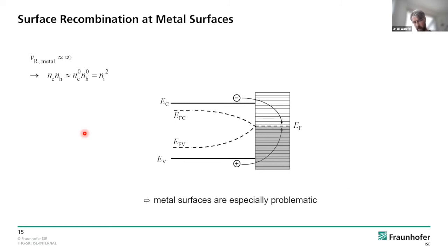At metal surfaces, it's especially problematic. The reason being that the metal has a Fermi level, which means that more or less all states until this Fermi level are occupied, and towards higher energies, nearly all states are empty. Usually with any kind of metal, you will see that an electron in the conduction band of the absorber is above the Fermi level of the contact, and the hole in the valence band is beneath it. So an electron will always find an unoccupied state energetically, and from there it can go down quickly to the Fermi level. And the same with a hole, which is an unoccupied state.